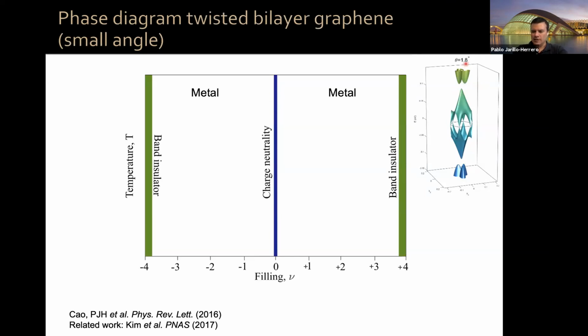This is for 1.8 degrees here. There is a set of Moire mini bands. They're not yet very flat, but they're a little bit flattish. And there are already single particle band gaps that appear that separate the central Moire mini band from the other remote mini bands, okay?